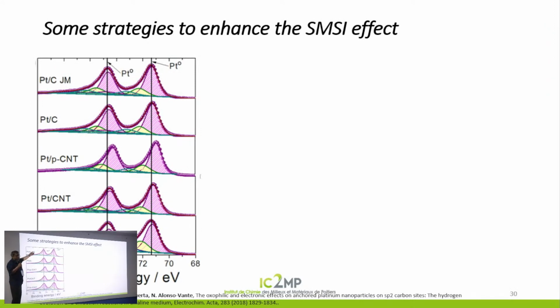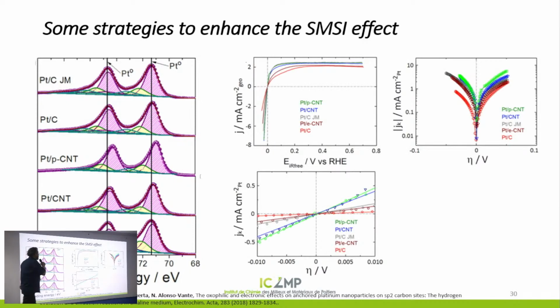Here you have the XPS measurement. Here is the benchmark material. Here is the material photodeposited on carbon. And here are the different carbon nanotube supports with different sp2 content. What you observe is an important shift toward lower binding energy. It's not that platinum becomes -1, that does not exist, okay? It means the electronic effect on platinum is not the same depending on the support that you use. Indeed, when you measure the oxidation of hydrogen and the reduction of proton, you see how this reaction is affected.